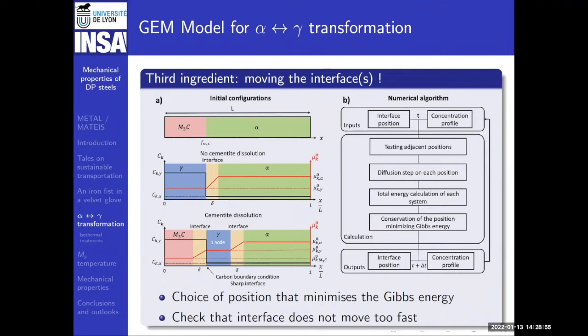So simply, the movement of the interface is the one that will minimize the Gibbs energy. So if the interface is here, the model is going to check: if I move it here, will it minimize the energy? No, okay, I don't move it. If I move it here, one step backward, will it minimize the energy? Yes, no. And we choose the position that will minimize the energy.